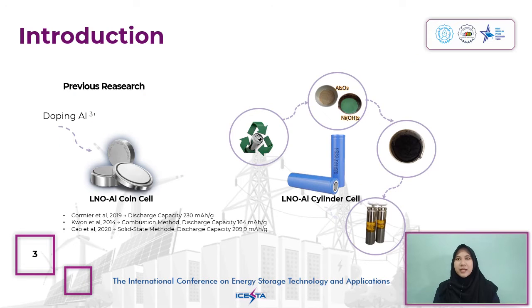Further research about nickel and aluminum substitution has been done by Cormier et al. with 5% aluminum to improve the thermal stability, with a discharge capacity of 230 mAh per gram. Moreover, research by Kwon et al. could suppress the transition of the nickel phase, with a discharge capacity of 164 mAh per gram. The aim of the research is to create a cylindrical battery with a cathode material that has a lower cost, is efficient and eco-friendly, through the extraction of aluminum from beverage cans as a cation dopant to improve material stability and electrochemistry performance.